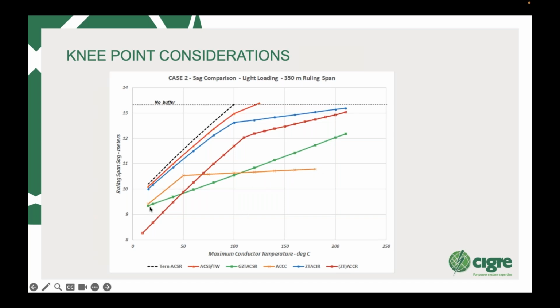The next one is your gapped. And you can see the gap has no knee point. So it depends purely on the metal as to how that goes forward. Now, the ACCC is stopped here at around about 180. A number of the polymers have an issue of changing the core composite above a certain temperature. So you can't run that normally to 250, whereas you see the others can go a bit higher. So depending on what you want, if you need to go above 200 degrees C, you might need to use some other kind of conductors.